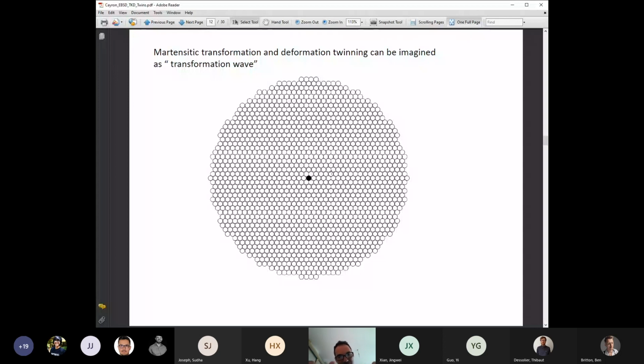So to me, it's as if you were with a hexagonal stacking everywhere, and you start forming a martensite of a square lattice in the core of the grain. And what is in between is the accommodation between your hexagonal lattice and your square lattice. And look, there is no dislocation here. Everything is continuous and elastic. It means that you can introduce a continuous rotation field to adapt the incompatibilities between your martensite, here a square martensite, and the surrounding grain, that is the austenite, here hexagonal.